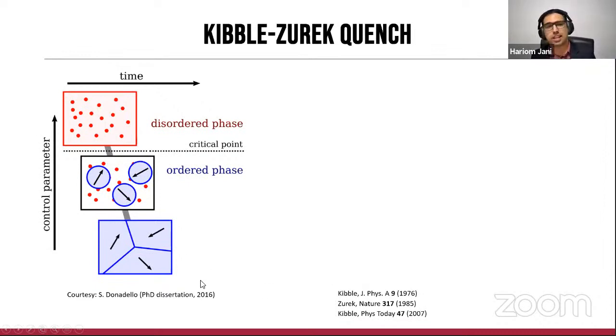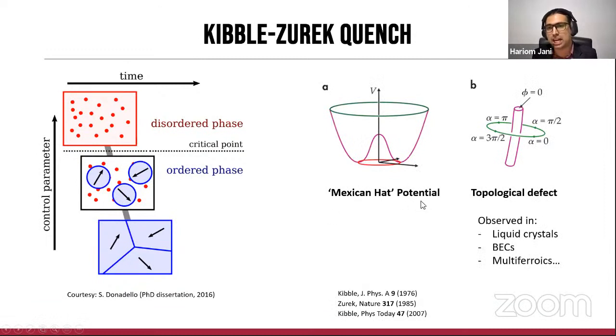Often this would result in trivial kinds of domain walls, but probabilistically it would necessitate that the textures of the domain orientations emerge in very special configurations to stabilize topological objects. So one example is that of a Mexican hat potential. If we were to have the energy ground state as a ring, mathematically symbolized by the U(1) symmetry, and all the magnetic orientation is along the basal orientation, it may be possible to actually trap a topological defect in the center, which is energetically unfavorable, as shown in this case here.